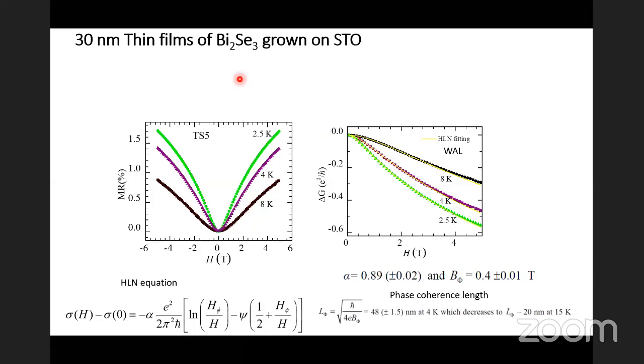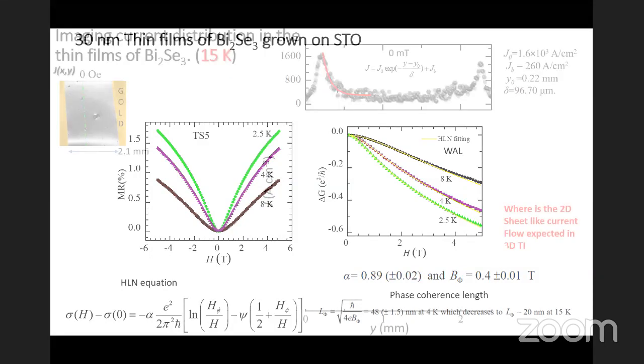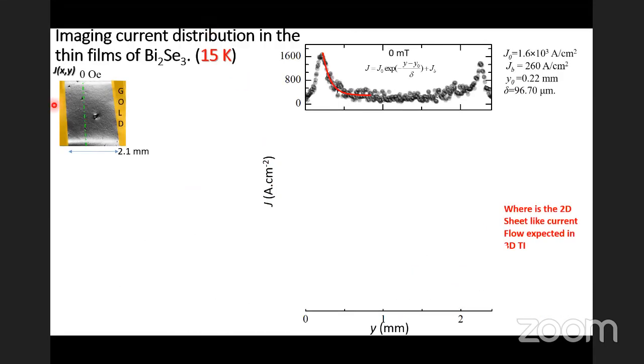So now what we do is that we apply this imaging technique to actually image the current distribution in this thin film. The first image that you see on the left here is an image of the thin film which is carrying current. And this is directly the current distribution that I'm showing here. What you can see is that there are very strong currents which are flowing along the edges, and there is almost negligible current in the middle of the film.